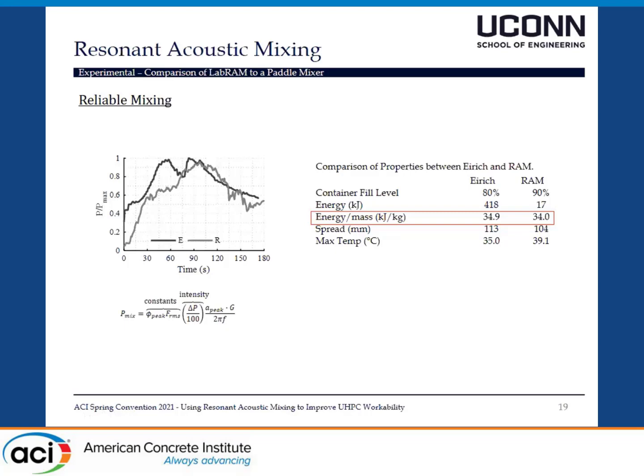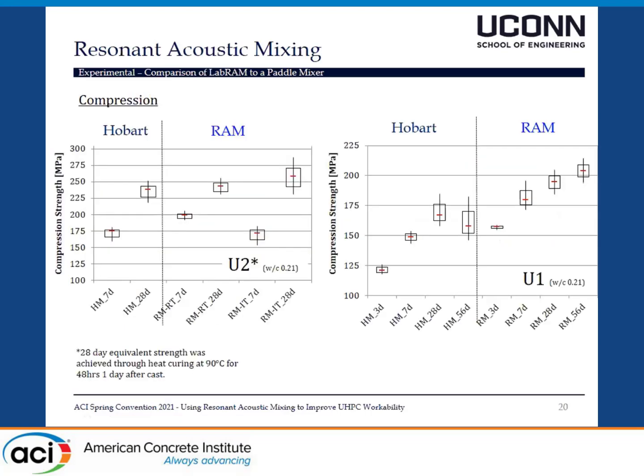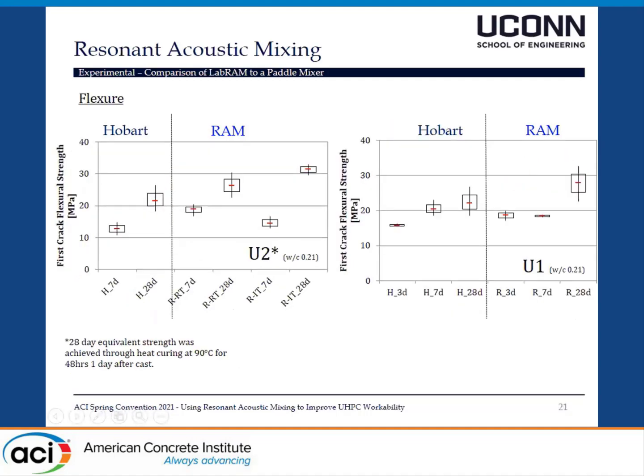Now, what about mechanical properties? For compression results, for example, the RAM gave similar or even improved compressive results. At 7 days, the RAM is roughly the same, but by 28 days, it's improved a lot. And the same thing for flexural strength. For 7 days, it's about the same, but then by 28 days, we're seeing an improvement in properties as well. So we can say at best that RAM does give comparable results and even improved results.